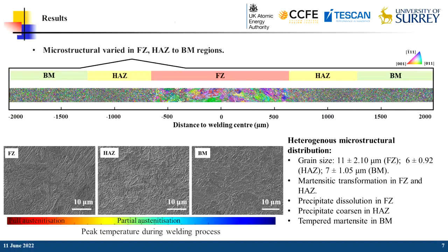So, the grain morphology of the as-welded Eurofer97 steel is illustrated by the EBSD orientation map, from the base materials to the heat-affected zone areas to the fusion zone. And the microstructure can be seen in the SEM images at the bottom left. The grain size has been quantified, and the average size is about 11 micron in the fusion zone region, 6 micron in the heat-affected zone region, and 7 micron in the base materials region.